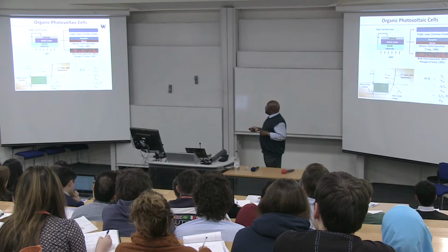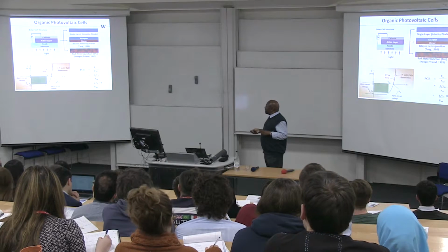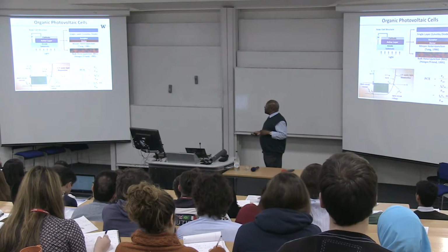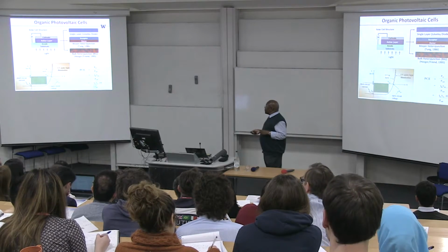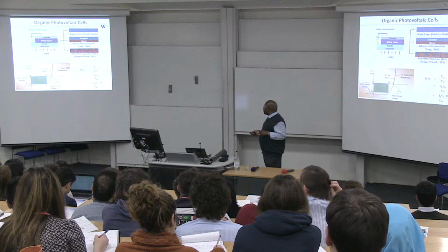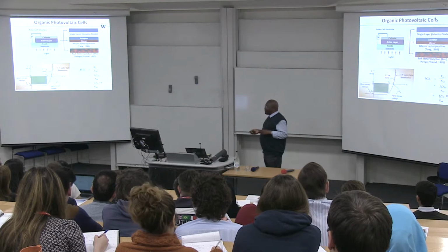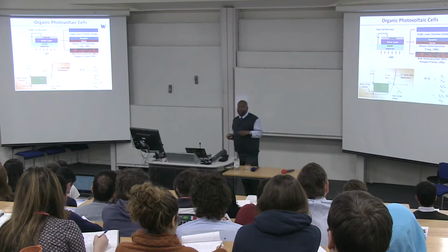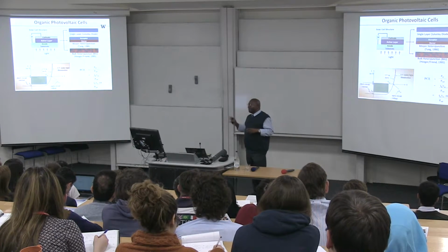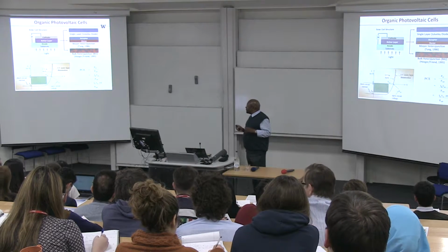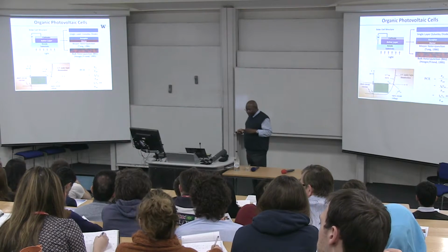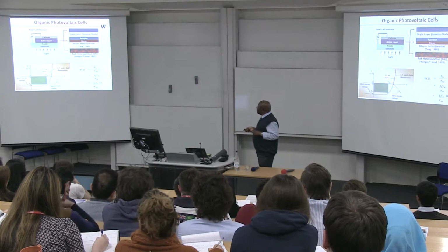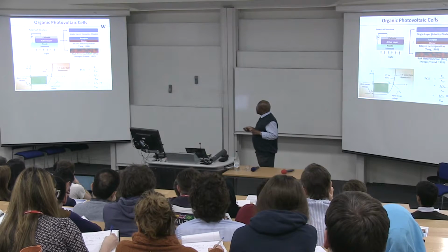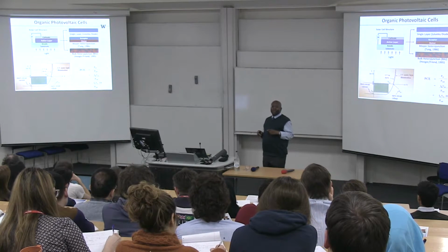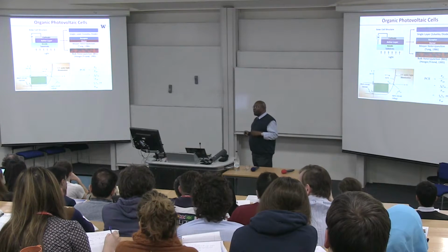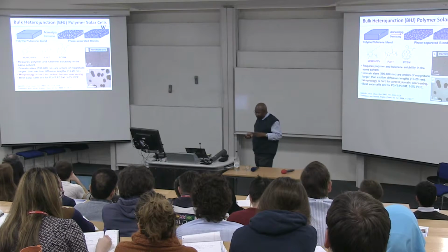All right. The typical measurement that we do from a solar cell like this is the current-voltage characteristics, from which we are very interested in, for example, the open circuit voltage and the short circuit current, from which we can figure out the power conversion efficiency, or PCE. You will be seeing these metrics as we go along, and some of the big challenges in the field, in fact, is really trying to understand and control these polymer blend systems, or bulk heterojunction films of these materials. All right.